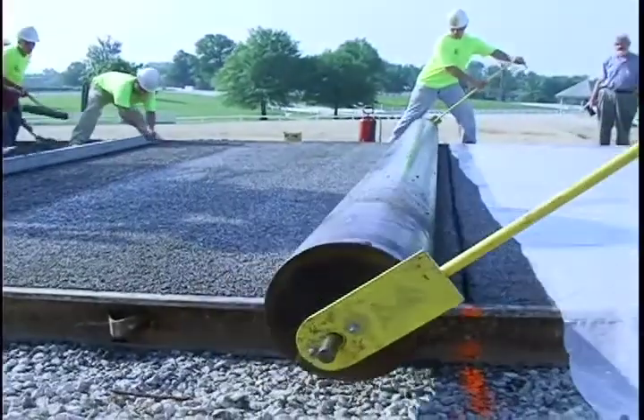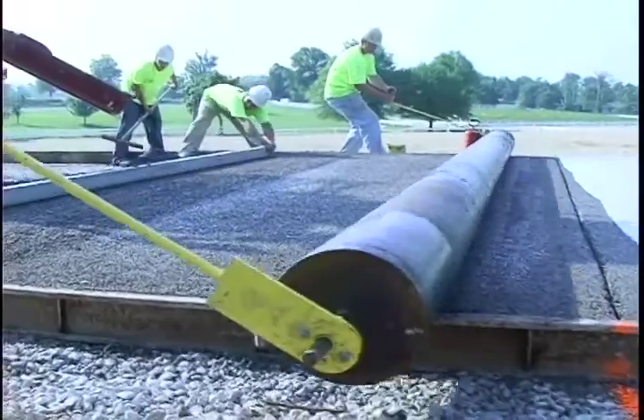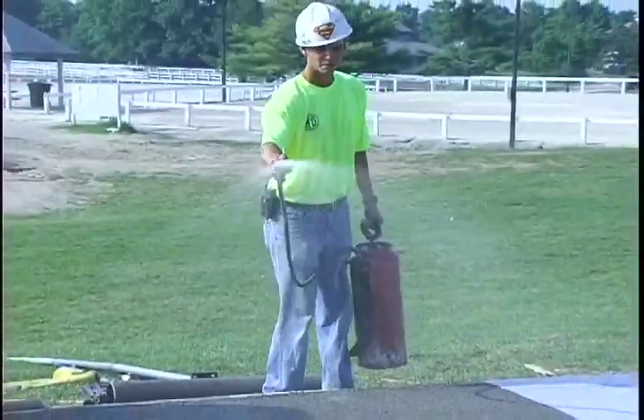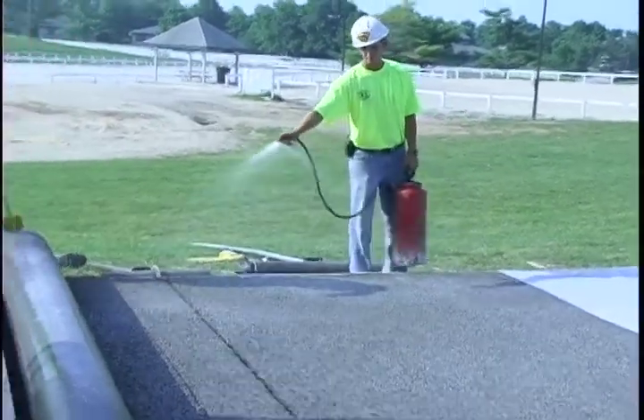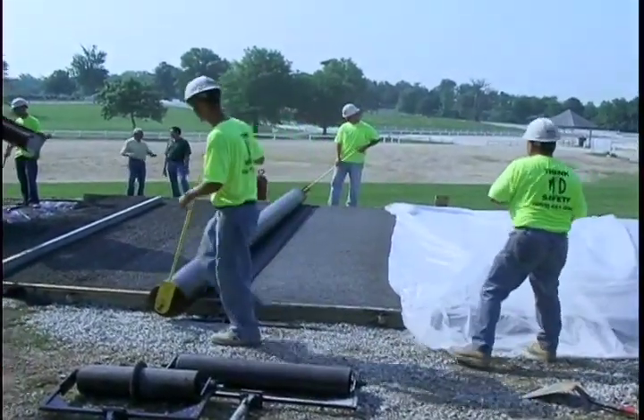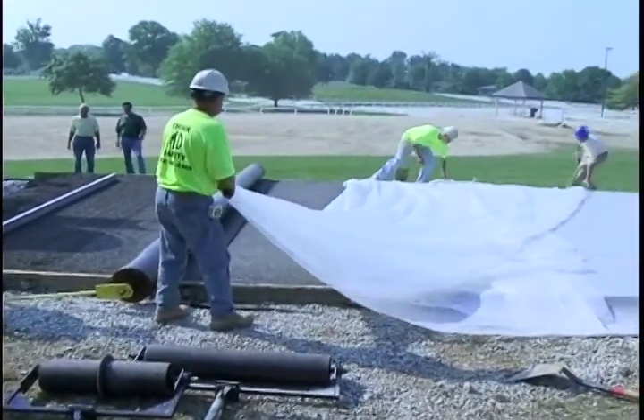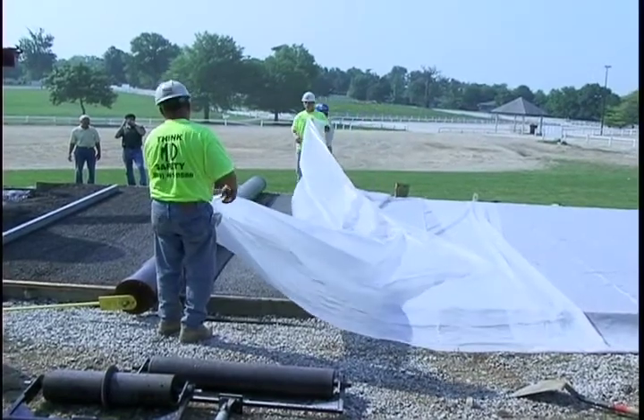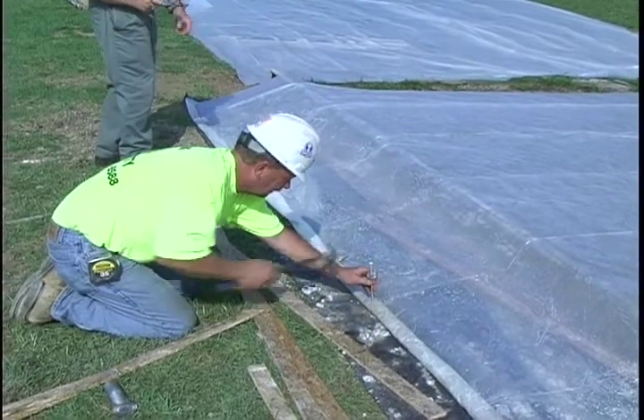For a horse pad, the dry concrete is not excessively compacted to ensure good porosity. A biodegradable bean or vegetable oil is used during the finishing process, which allows the concrete to stay moist and cure properly. Plastic is then placed over the concrete to help retain moisture and to continue the hydration process. This goes on for one to two weeks depending on the weather conditions. The curing process will continue for another 28 days.